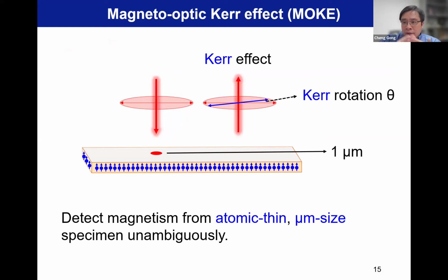So the methodology I use is called the magneto-optical effect. And then we also use magnetic circular dichroism. I will quickly explain this methodology. As you can see, if the material is a magnetic thin film or 2D magnet, you have ordered spin. And then when you shine linearly polarized light, the linear polarization represented by this line with double arrow, the electric field of this light is just along this direction. And then due to this orbital and spin orbit coupling, you will have a rotation when the reflected light is examined.